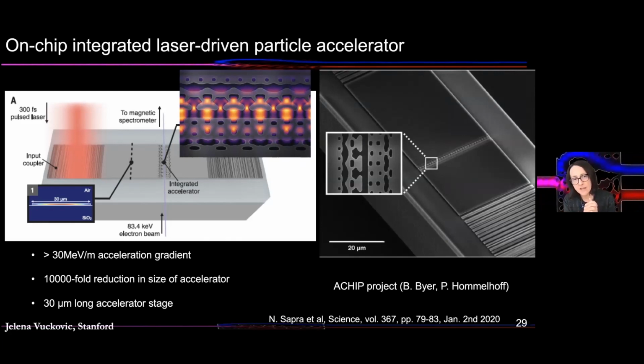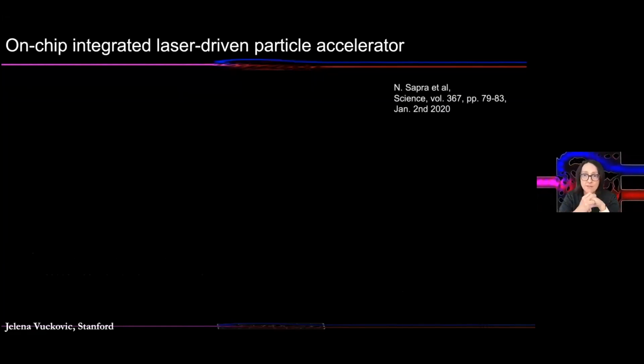So this is a 10,000-fold reduction in size, but when we characterize it and measure, we actually see an acceleration gradient of 30 megaelectron volts per meter, meaning that an electron propagating through this structure would get energy of 30 megaelectron volts per meter of length. And within an inch, we could go from the input energy of 80 kiloelectron volts to megaelectron volts, which is already very useful for medicine.